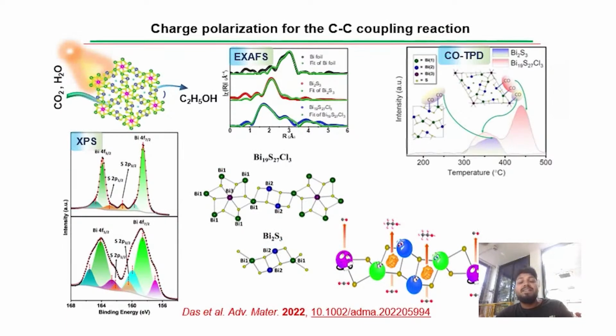Up to now, we have majorly exploited the heterojunction system. However, a single system can also give the C2 product if we can engineer the catalyst. Therefore, we have made the Bi19S27Cl3 catalyst, because this particular material has 3 different kinds of bismuth centers, which we have proved from EXAFS and XPS analysis. In this study, when we did CO TPD, we found in the case of Bi2S3 there is only one kind of CO adsorption. However, for Bi19S27Cl3, there are 2 kinds of CO adsorption.